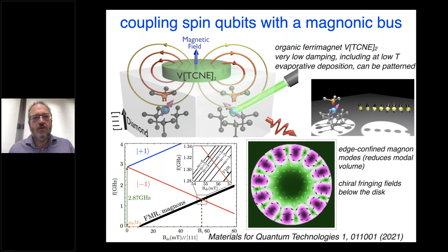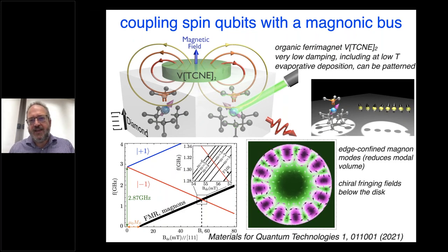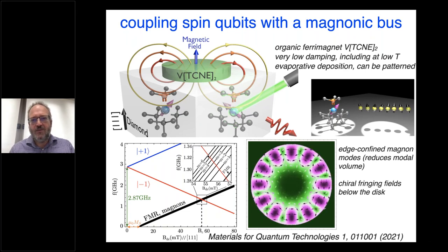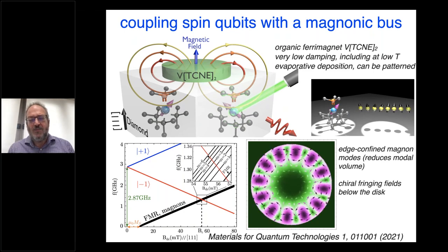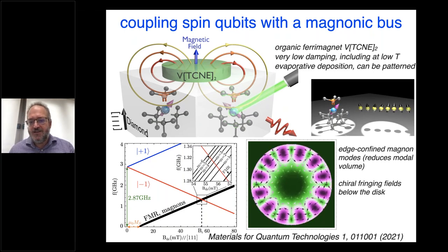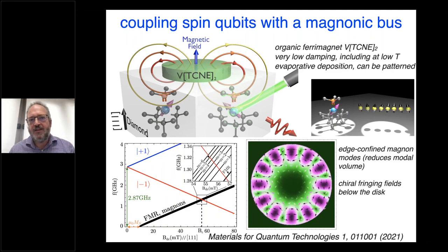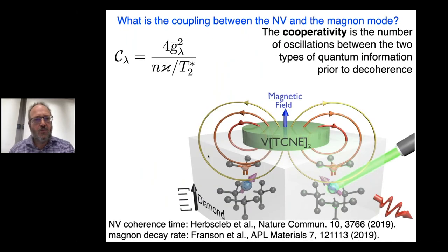And that's what drew us to the organic ferrimagnet, vanadium tetracyanoethylene. So this is perhaps a bit of an exotic material for many, but it has exceptionally low damping. The magnetic damping is lower than that of yttrium iron garnet, which is typically the gold standard. And since it's an organic material, it can be fabricated with evaporative deposition and can be patterned considerably more simply, much simpler than yttrium iron garnet itself. All right, so let's look at the metrics that are relevant for coupling spins to magnons.